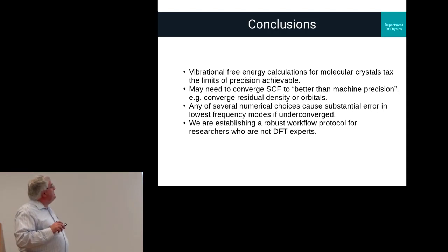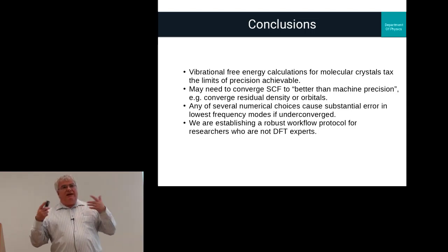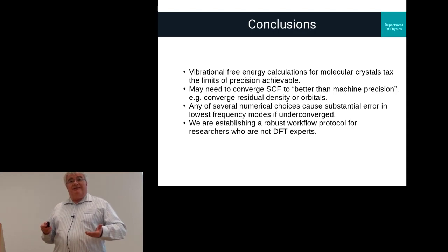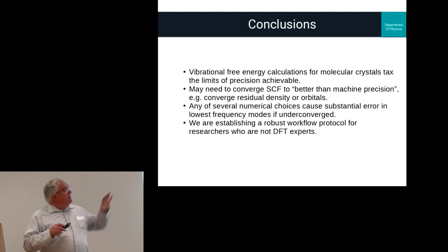To conclude, we can do vibrational free energy calculations from molecular crystals, but they tax the limits of precision that we can achieve. We need to push everything as far as we can get, and we may need to converge our SCF to better than machine precision. What do I mean by that? If we're used to thinking about an exit criterion for an SCF loop using energy as a proxy for convergence, maybe we're going to need to converge on the residuals of the density or the orbitals instead. That's what I mean by better than machine precision. We won't get an improvement in the energy number, but that's a proxy for what we really care about: the convergence of the density and the orbitals. Just about anything you can under-converge will mess up this calculation, so you have to get it all right every time. The goal is to try to establish a workflow protocol for researchers who are not DFT experts. Thank you very much.